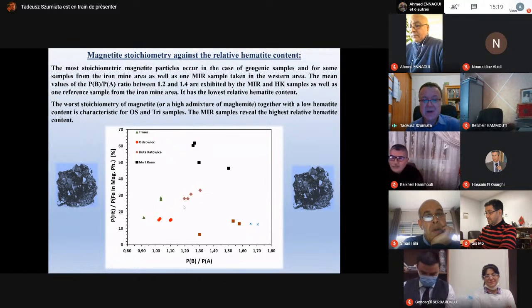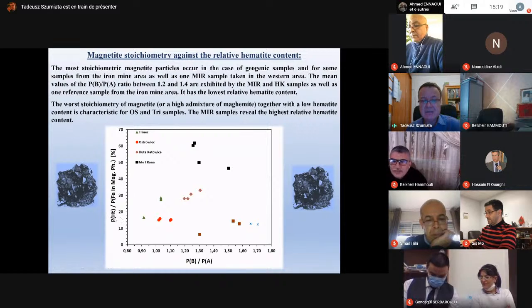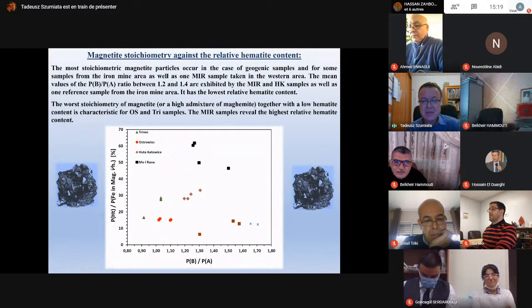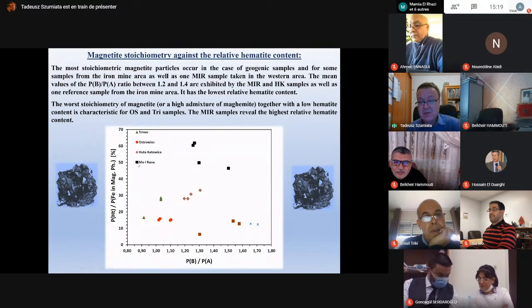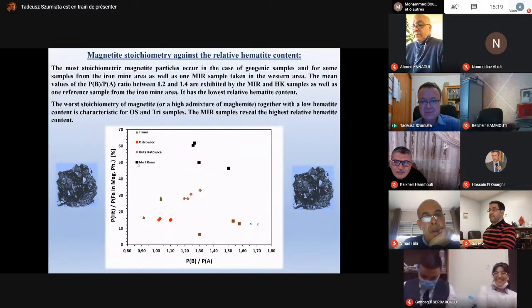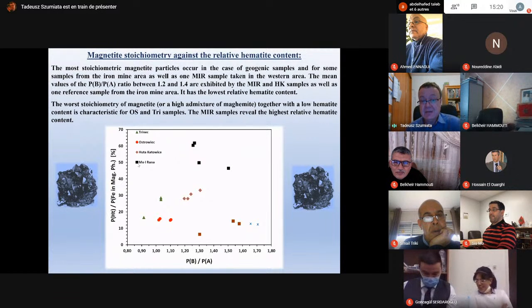You can also see the values of the contribution of the hematite in relation to all magnetic or ferrimagnetic phases, and the domination of hematite is visible in the case of this Norwegian sample, Mo i Rana, probably because in this iron ore dressing plant there was a lot of hematite, and it has been transmitted via winds to the forest, to the fields, and this influence is very clearly visible here.